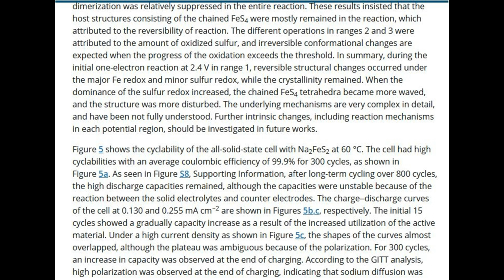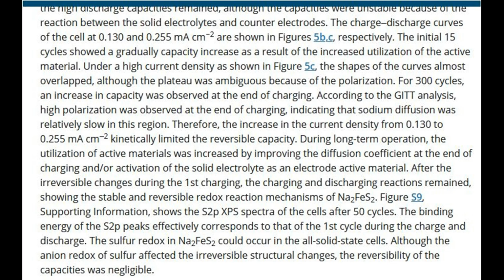According to the GITT analysis, high polarization was observed at the end of charging, indicating that sodium diffusion was relatively slow in this region. Therefore, the increase in the current density from 0.130 to 0.255 mA/cm2 kinetically limited the reversible capacity. During long-term operation, the utilization of active materials was increased by improving the diffusion coefficient at the end of charging and/or activation of the solid electrolyte as an electrode active material.